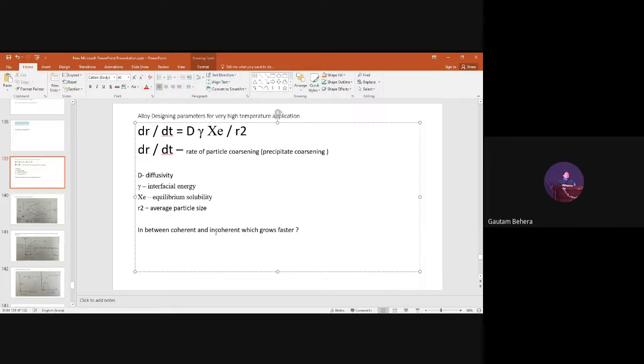So it is written, between coherent and incoherent, which grows faster. Actually, coherent particles and incoherent particles: basically, incoherent particles grow faster because of the high interfacial energy they have. But the coherent particle size is smaller. If it is of intermediate size, then it is good. But if it is very small, it will grow faster. To minimize the interfacial energy, they become bigger and bigger. And if you remember, the incoherent particles take a spherical shape so that they can minimize the interfacial energy.